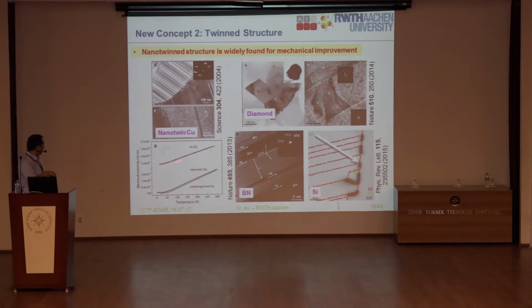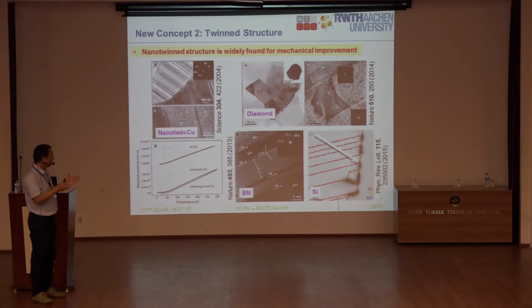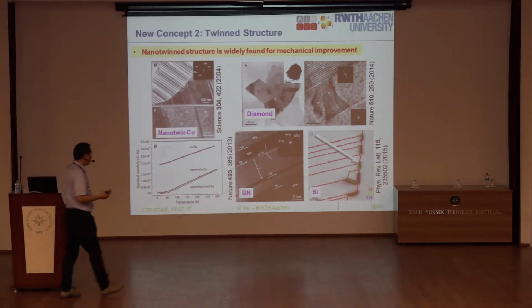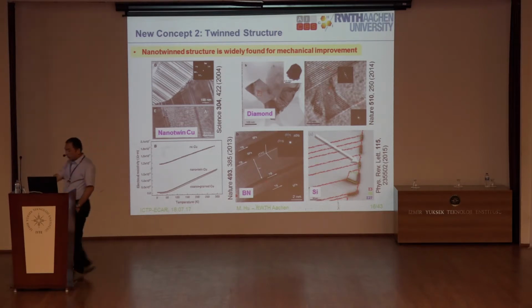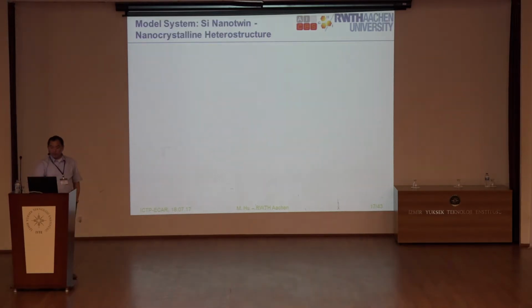And then we also found that the electronic transport property does not change too much if you have nano-twin. So this is very, very promising, very exciting for the electronic, right? So then an intuitive idea is how we can transfer this idea into the semiconductor. If you introduce the nano-twin inside the semiconductor or the thermoelectric material, and we can maintain the electronic transport, and in the meantime reduce the phonon transport, then that will be fantastic, right? So we use a model system of silicon.